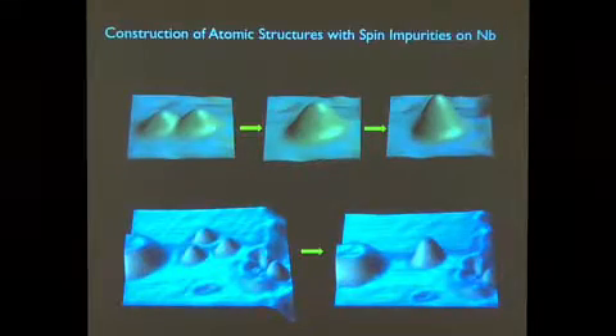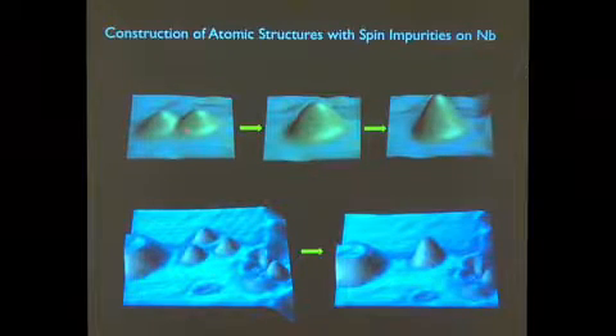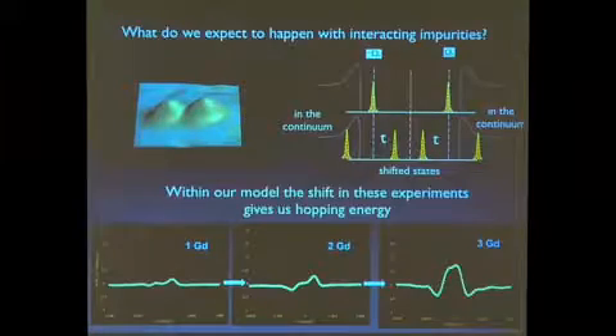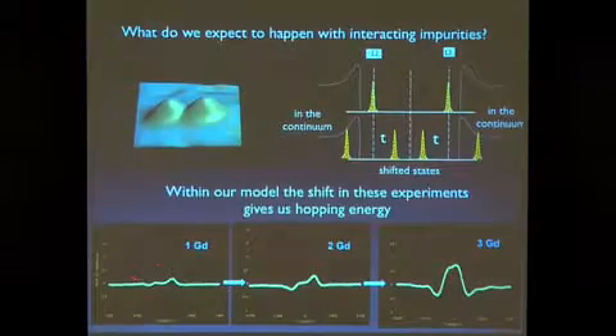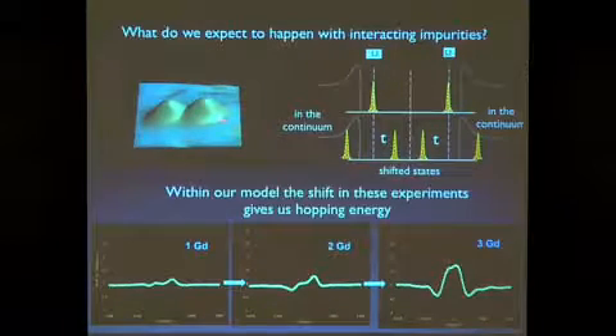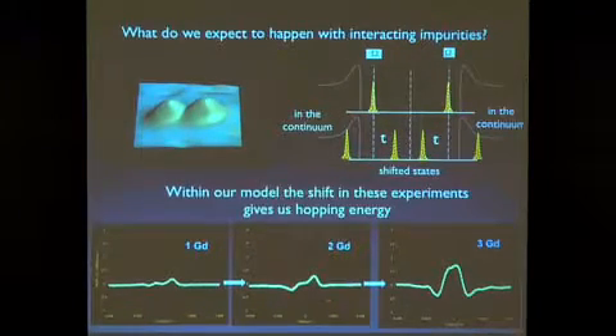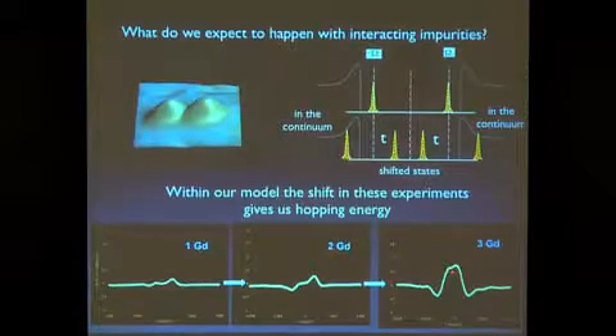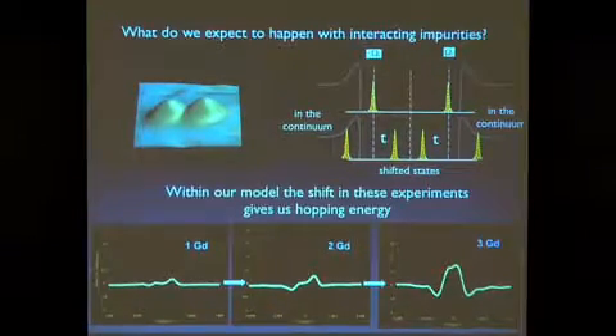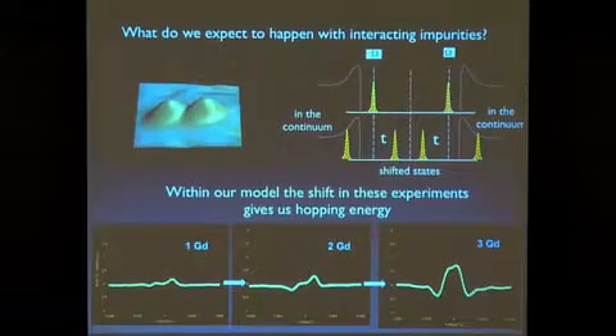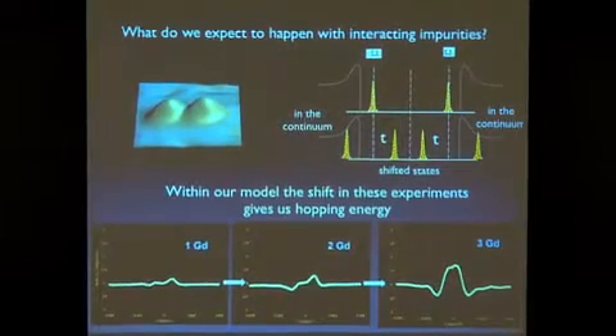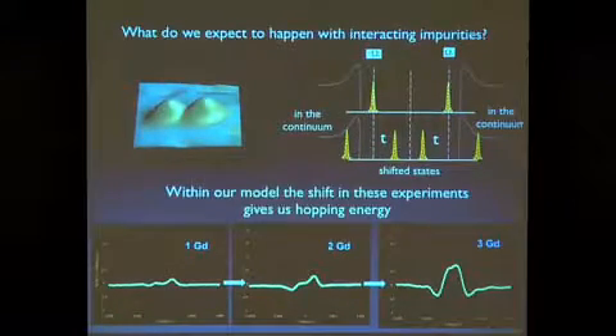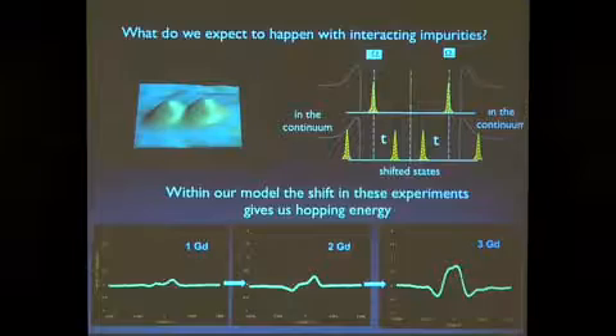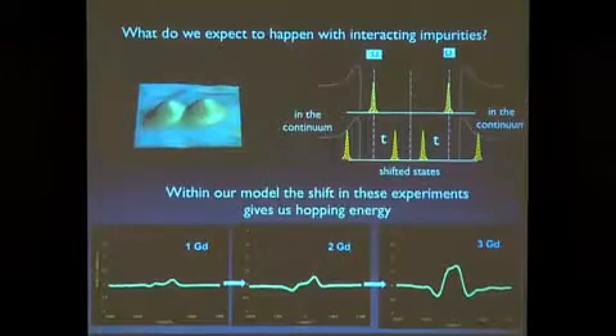So this experiment has gone on the way, and we are basically building structures in which we can study the interaction between these spin impurities by building structures with different numbers of atoms. And what we find is that indeed, if you look at these states, as you couple them together, you start to change the nature of the bound state. You can get the state to move closer to zero. You can split these states. And the details are still being worked out. But experimentally, what's promising is that you can clearly see changes and interaction between these localized states when you bring the spins close together. So this is our first step.